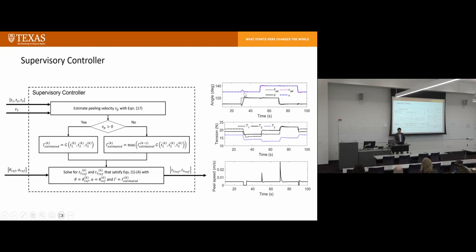But you see there are still errors between the desired angle and the actual angle. What happens is, during the process, we estimate peeling speed, right? If there is a desired angle change, the peeling front may not happen anymore, because during that period of time, the configuration of T1, T2, and T3 doesn't satisfy the peeling condition. So the peeling front has to move to another location. During the move, you're trying to approach the criterion where your strain energy release rate is equal to the adhesive energy, and then your peeling will happen again. So there's a period of time where the peeling front velocity is 0, and then after your peeling configuration is shifted, you can start to peel the graphene again.